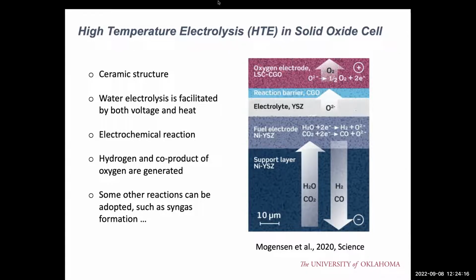This picture shows the structure of the solid oxide cell. It contains a few ceramic layers. In the middle, you can see an electrolyte, and at the bottom and the top, there are 2 different electrodes. The water will be fed from the bottom side, and because of the catalysis, water can be split at the electrode site into protons and oxygen ions. Depending on the category of the electrolyte, the oxygen ion will transfer through the electrolyte membrane to the other side to form oxygen.